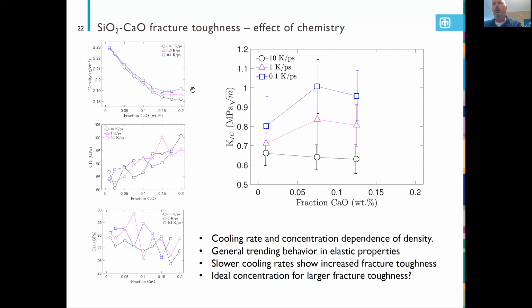And that's kind of an expected result, in the sense that if we slow the cooling rate down, we should find a material that is stronger, denser, and a more well-equilibrated configuration. The idea is that high cooling rates often lock in non-equilibrium states within the glass, and by slowing that cooling rate down, we will actually densify the material. So this is an expected result. We can look at some of the elastic properties, for instance, C11 and C44. C11 is related to the elastic modulus, whereas C44 is related to the shear modulus.